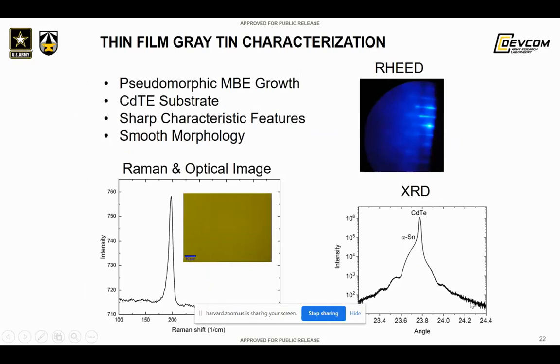But using RHEED and some X-ray diffraction and so on, Raman scattering, we can identify when we have alpha tin quite nicely. The Raman peak is actually quite definitive. And it allows us to tell at this energy that we have alpha tin as opposed to beta tin, which doesn't show any Raman signal at all. And this is a photograph, although on a large scale, of the surface, which looks like it's reasonably decent material.